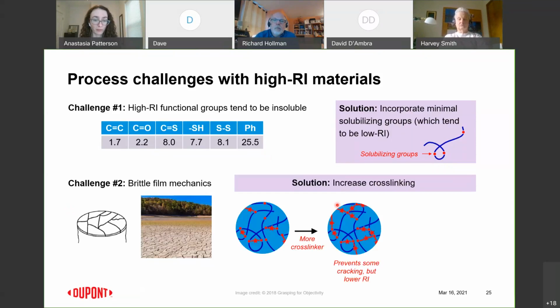So, if you zoom in on the cartoon version, we had some amount of crosslinker that we had optimized for in the beginning, but in order to prevent the cracking, we increased the crosslinker. We added more of that small molecule. But of course, that molecule tends to be low refractive index, and so the more we add in, the more we're going to dilute the optical properties that we want to keep.